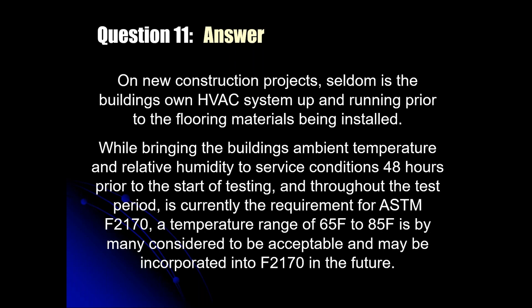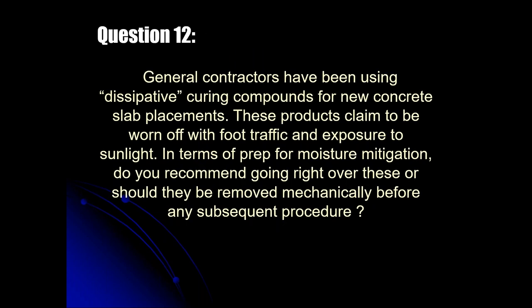But I do think you're going to see that 65 to 85 range that you see for calcium chloride testing become applicable to in-situ relative humidity. Right now it says service conditions. Question 12. General contractors have been using dissipative curing compounds for new concrete slab placements. These products claim to be worn off with foot traffic and exposure to sunlight. In terms of prep for moisture mitigation, do you recommend going right over these, or should they be removed mechanically before any subsequent moisture mitigation?